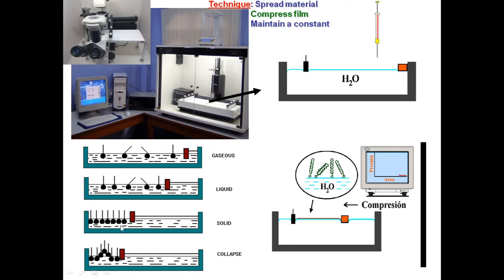How a stable Langmuir monolayer is formed at the air-water interface can be checked by the surface pressure versus area per molecule isotherm characteristic study. It is observed that when the molecules are far away, initially the surface pressure is very small. But when the barrier is closed slowly, at one point the surface pressure becomes steep. That is, surface pressure increases to a larger extent, but area does not change too much. When this steep rise of surface pressure occurs, we may say that a two-dimensional crystalline arrangement of the molecules occurs, that is, a Langmuir monolayer is formed. But after further compression, there will be a collapse. That is, the pressure suddenly falls and collapse of the monolayer occurs.